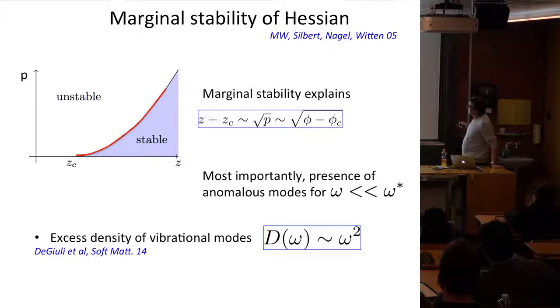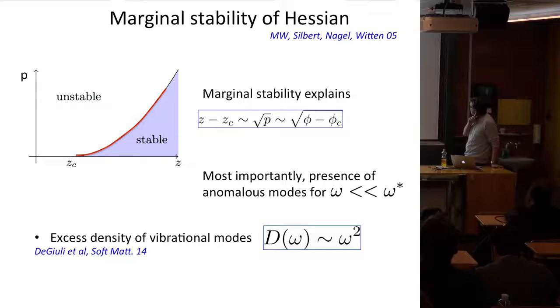Okay, so what we realize is that if you look at the predictions and you look at those packings, what you find is actually an observation: where you live on those packings is at or very close to this marginal line. So it seems that those packings are on the edge, they live on the edge of an elastic instability. They just have enough contacts to balance the destabilizing effect of pressure. This explains immediately two aspects. It explains the scaling relationship between coordination and pressure. But this scaling alone would not tell you that you live right here, because you could be living right there or in the middle of it, for example.